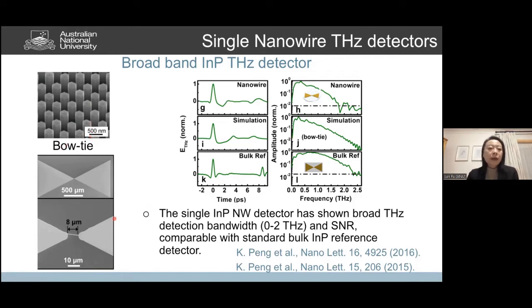So what we do is that we knock down the nanowires on a substrate, and through photolithography, we make this bow tie antenna across each end of the nanowires. You can see from here. And then we measure the terahertz response through the terahertz spectroscopy system at Oxford University, through our collaborator Professor Michael Johnston's group, where we can see that from the nanowire, we are able to detect a quite broadband terahertz wave, with broadband detection up to 2 terahertz with very good signal to noise ratio.